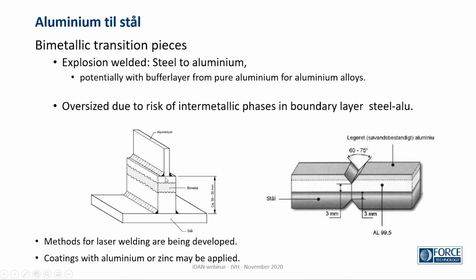bimetallics, they are often called in English, where you have the steel, the aluminium combination layer, and the upper part also aluminium. And then you can weld steel to steel and aluminium to aluminium. It's also exemplified in this where you can see the steel, the pure aluminium as an intermediate layer to have these alloyed aluminium on the top, one with more strength and more corrosion resistance. And these have been explosion welded together as a part you can buy for making this combination.